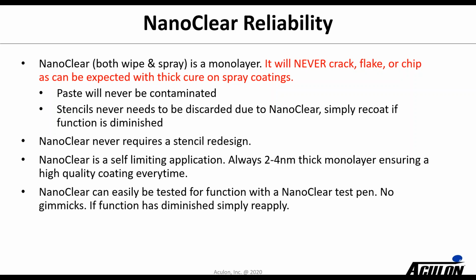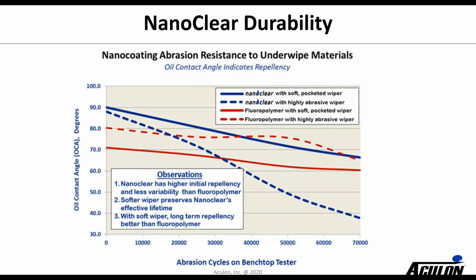It is a self-limiting application, so it is always going to be a high quality 2 to 4 nanometer thick monolayer coating within the apertures. And if there's any concern over whether the stencil is properly coated, we sell a simple NanoClear test pen, which is simply a dyne pen that can be wiped across the stencil in a matter of 2 seconds and is a very, very quick black and white test on whether it is coated.